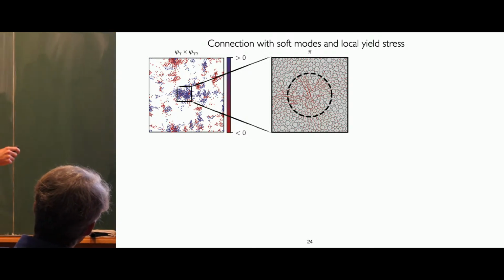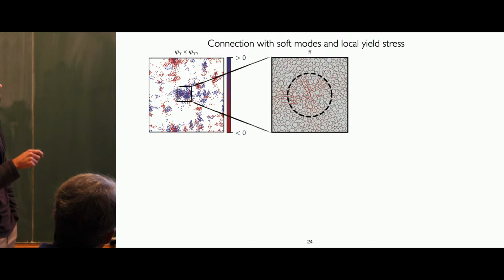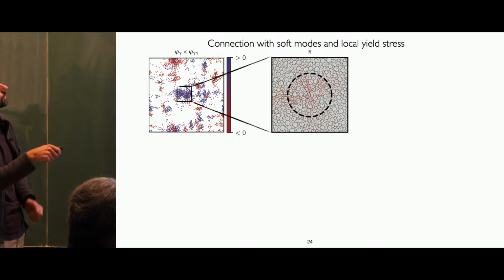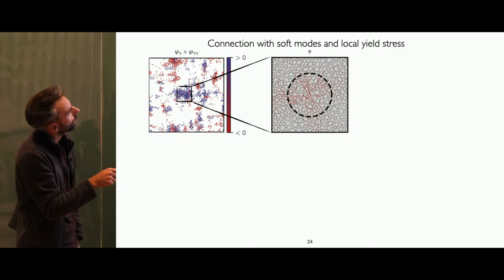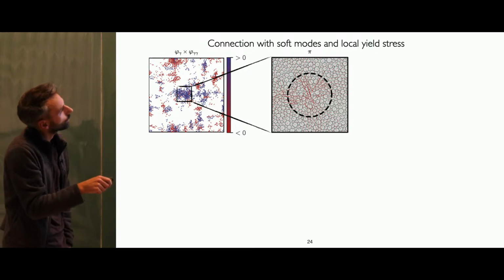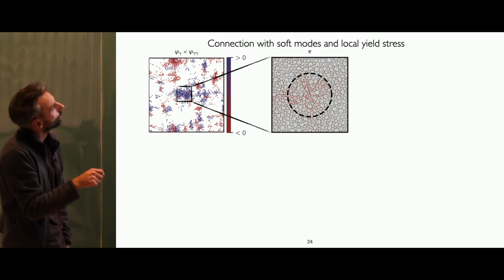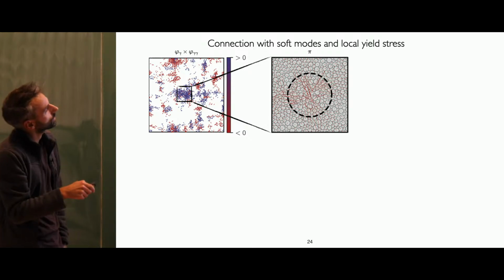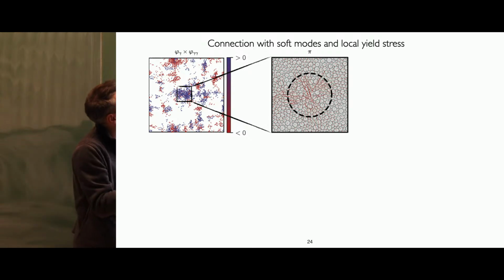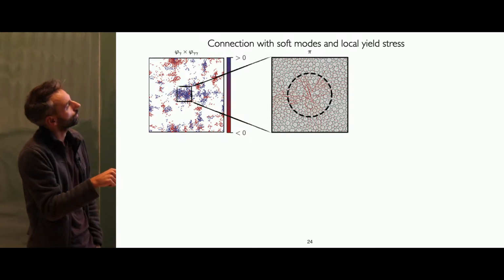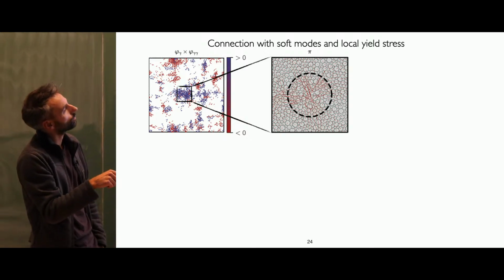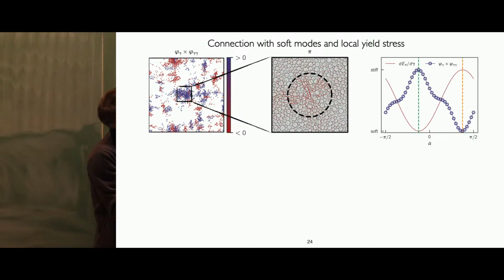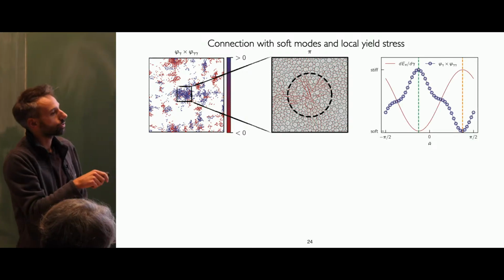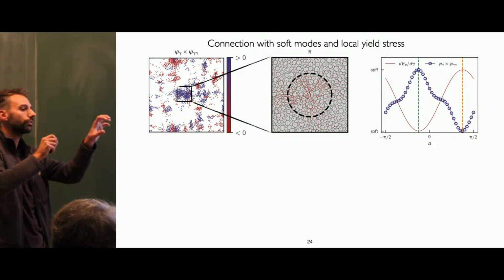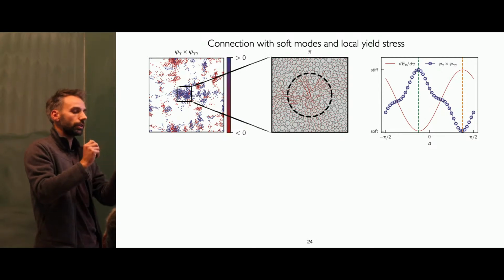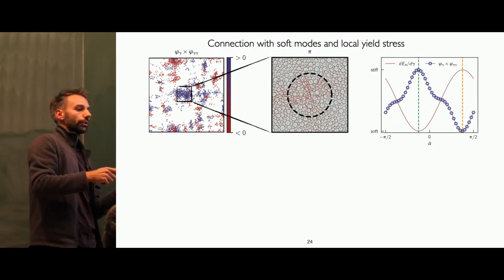So I will just show one example. I'm taking the same glass, and I'm taking this soft spot which appears to be blue, so good coupling with positive simple shear. Now I'm going to this soft spot, I'm going to find a mode, and I will compare the micromechanics of the mode to the polarization of this indicator. I don't have the complete micromechanics of nonlinear modes, but I can at least work out the first coefficient, which means how the energy of the mode will change with the strain. So I can already tell you if I have a mode at small strain, is it going to stiffen or is it going to soften?